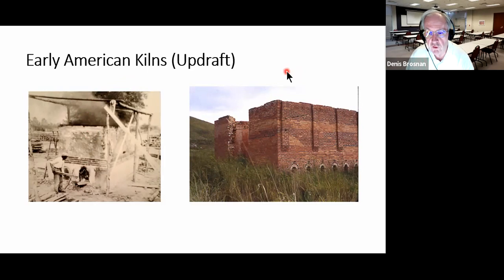The other picture is a picture of a scove kiln, which also was an updraft kiln. If you look closely, you can see openings for burners right at the base of the kiln. And it had a permanent brick structure forming the outer walls. So the bricks were laid on the inside and stacked up, and then the furnace was fired. Of course, the firing cycles here were typically around a week or perhaps 10 days or so. It took a long time for the ware or the bricks inside the kilns to cool off so that they could be handled to be taken out.